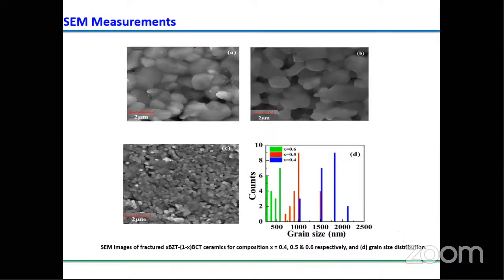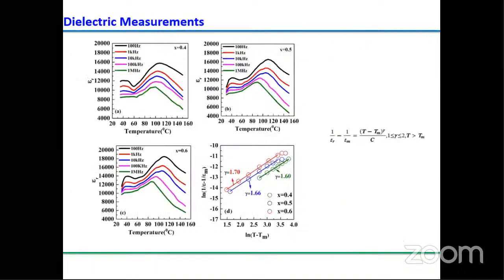These measurements represent SEM, scanning electron microscopy measurements. When you observe this SEM, here we observe that the grains are all compact. The grain size is decreased with increasing composition. When we increase x to 0.6, zirconium will be more. This zirconium hinders the grain growth. As a result, we will get these small grains. These small grains will improve the relaxor behavior. That is what we can observe in the next few slides.